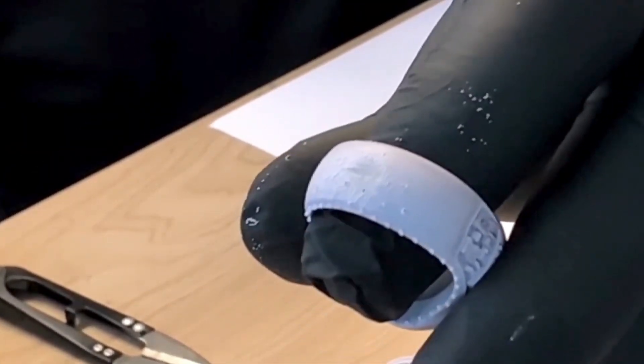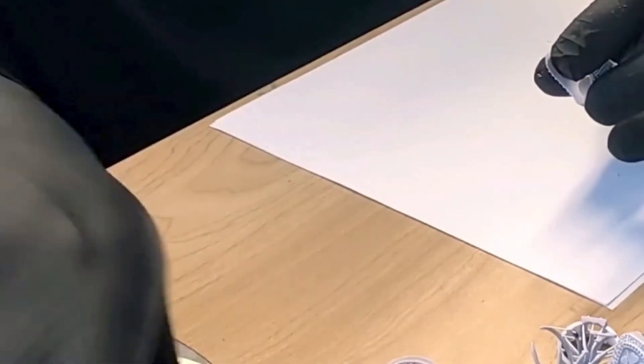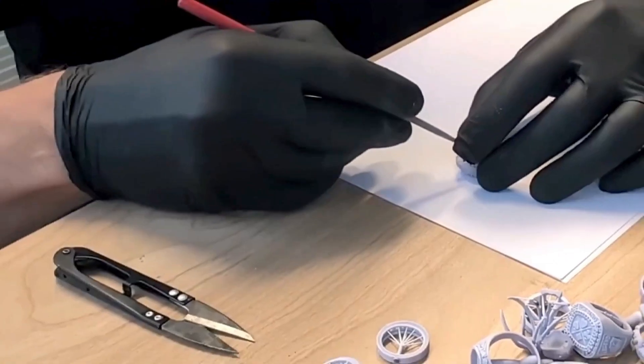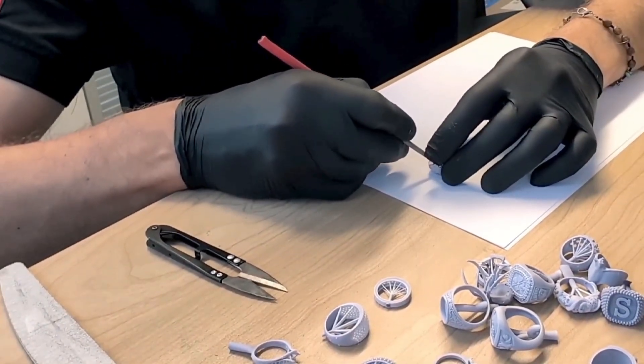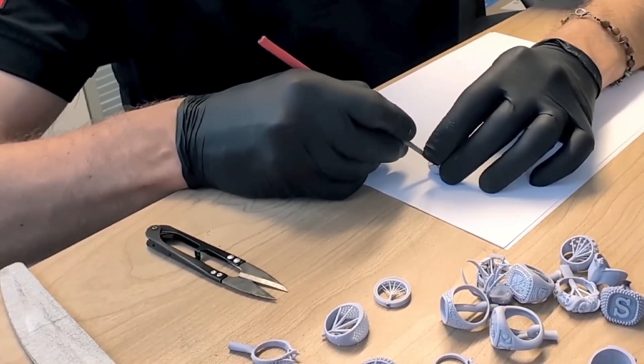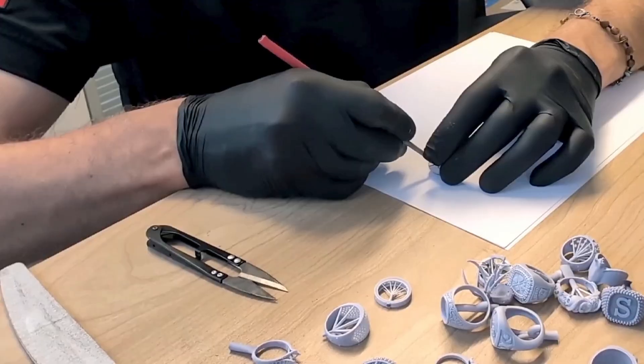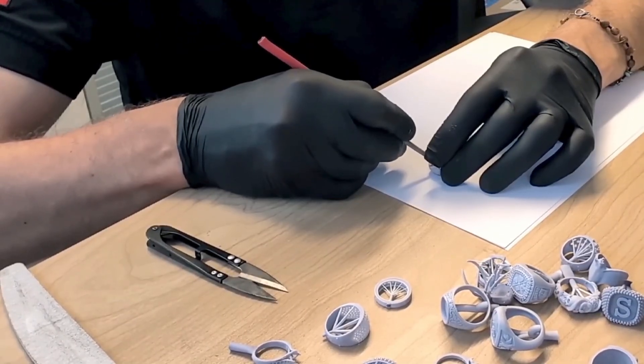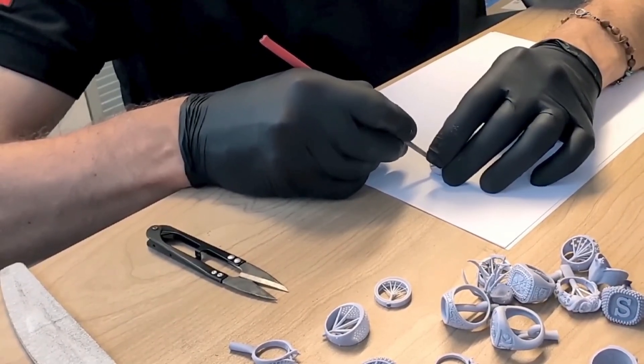Consequently, I am sanding the models with a coarse grit exactly at the point where I want to weld the wax rod. I'll let you know right now that over that point, we'll melt a small amount of wax to ensure a perfect bond between the wax rods and our patterns. What I want to avoid are small cavities, holes, or empty areas where the investment can dangerously collect.